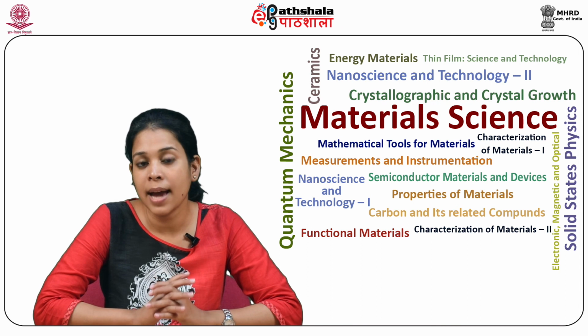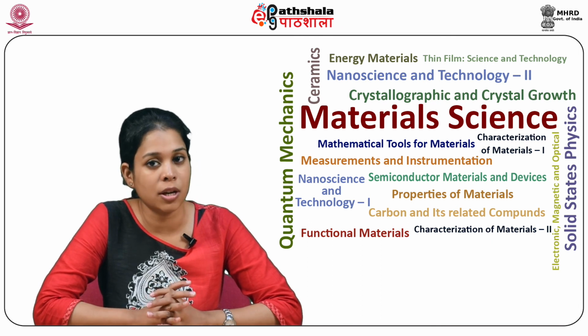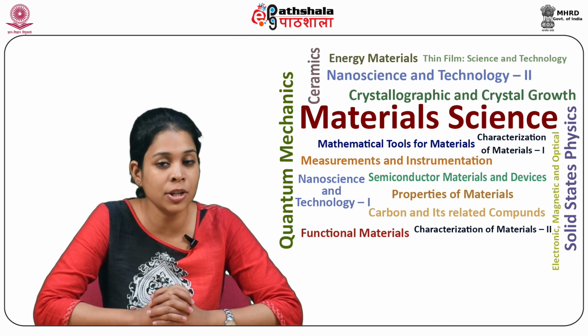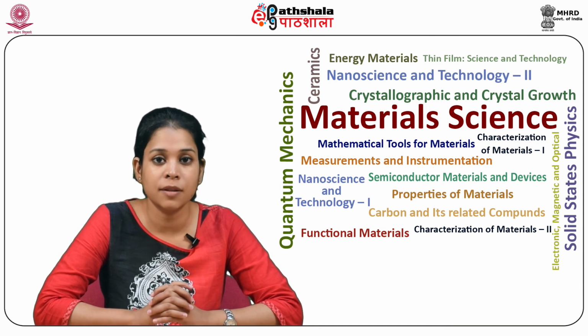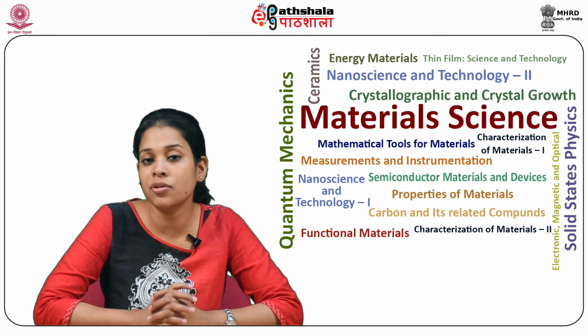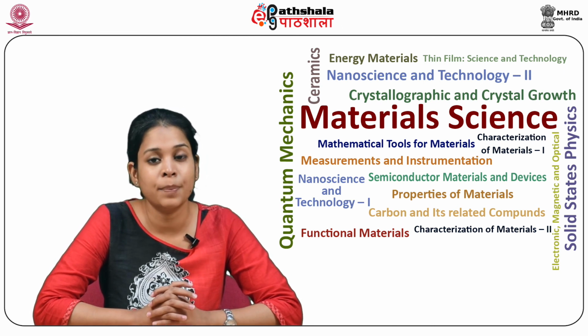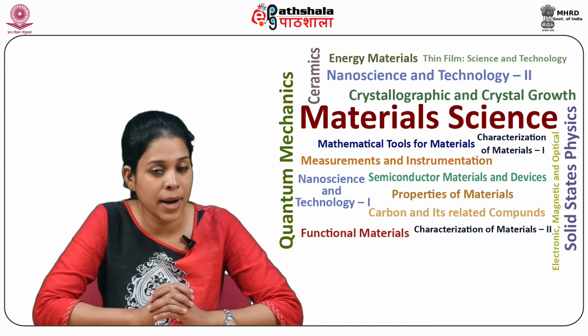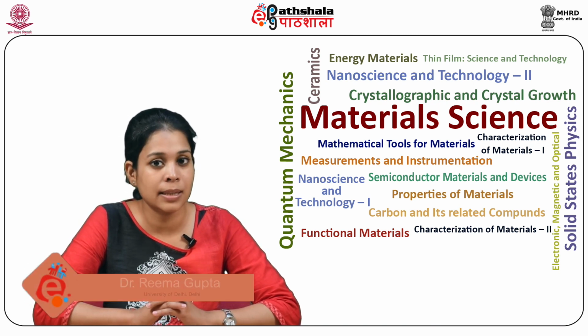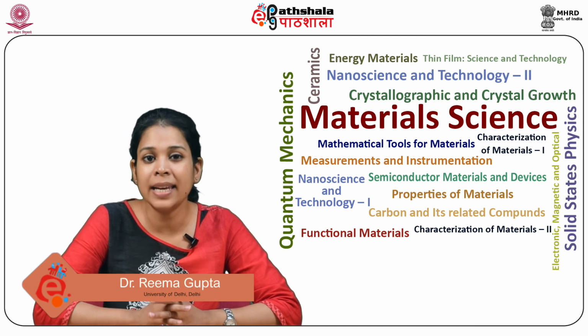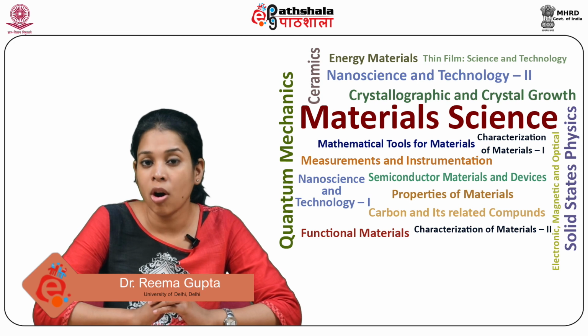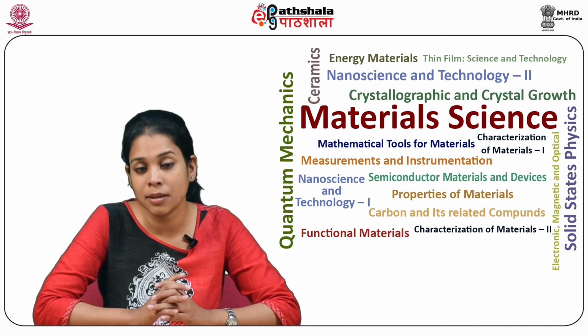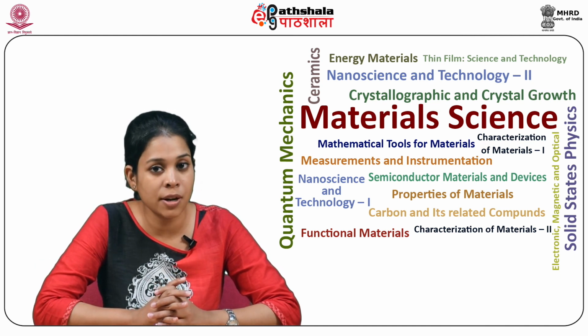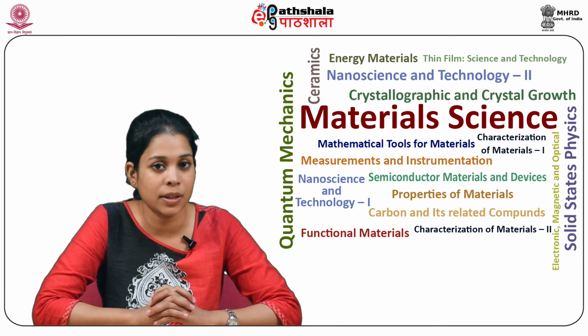So the fast ion conductors have open structures resulting in lower migration energy for defect diffusion, permitting fast transport of ions such as in beta prime and beta double prime alumina, resulting in high electrical conductivity of the order of 10 to the power minus 1 per ohm per centimeter over a temperature range of 300 to 675 Kelvin. Thank you.